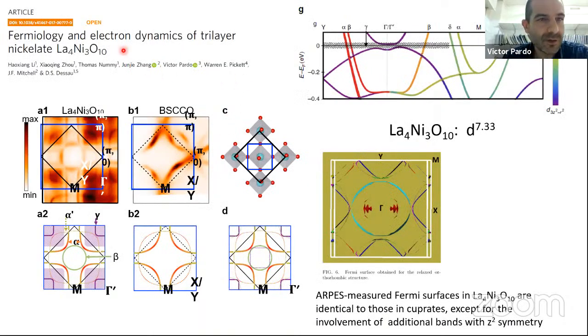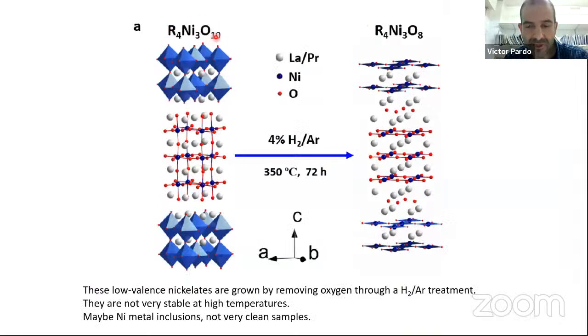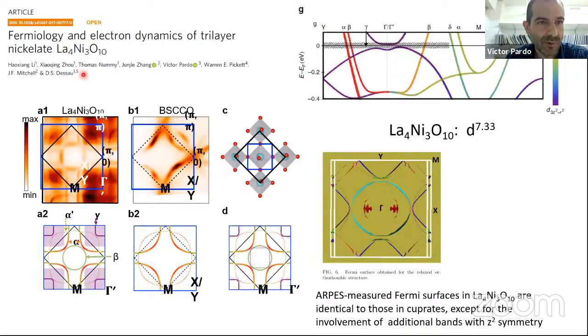It's normal. So we even started, remember we come from this Ruddlesden-Popper, we first started one of those without removing the oxygens, and we found interesting physics here. You can see that when you measure with ARPES, which is what Dan Dessau did with his group in Boulder, what you see with the Fermi surfaces of these 4-3-10 is that, like in the cuprates, you have these sheets of the Fermi level. You find them in the measurements that they did, but you have additional bands. You have many additional bands, which are basically d z squared in character.